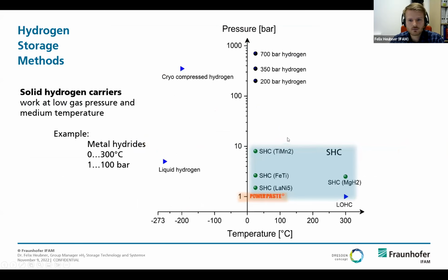Metal hydrides or sorbent storage have the main advantage that hydrogen is bound to the materials. So on the one hand, it is a very safe storage way, because hydrogen is not only available in the gas phase and cannot be released during a leakage all at once. Hydrogen is bound on the materials, and so it's a safer storage. And in combination with the boundary conditions in terms of temperature and gas pressure, it can be even safer, because you often have only low gas pressures available at medium temperature ranges.